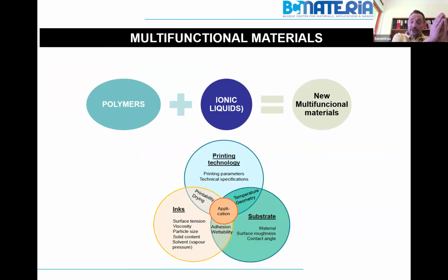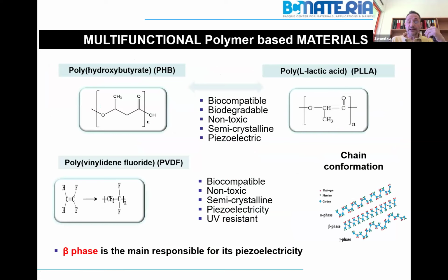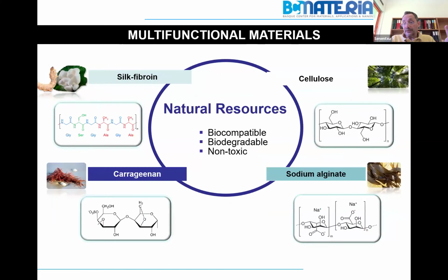As you tune the interaction between the polymer binder and the ionic liquids, you do not need basically anything else. And this is also a big contribution to sustainability. You have to choose the polymer binder and the amount. It can be inert or active. If it is active, it is basically synthetic, but if not, silk fibroin, carrageenan from algae, sodium alginate, or cellulose.